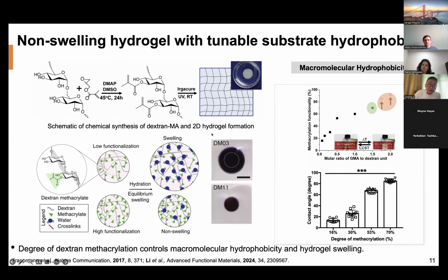It turns out that by changing the molar concentration of the GMA relative to the dextran units, you can change the methacrylate functionality, from the lowest of about 17% all the way to about 88%. The degree of methacrylation really controls the hydrophobicity of the hydrogels.